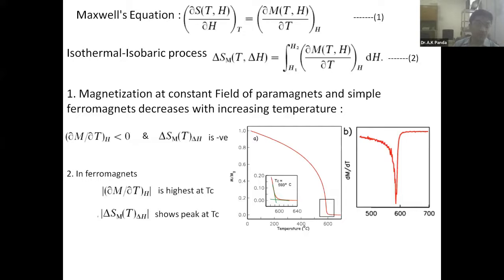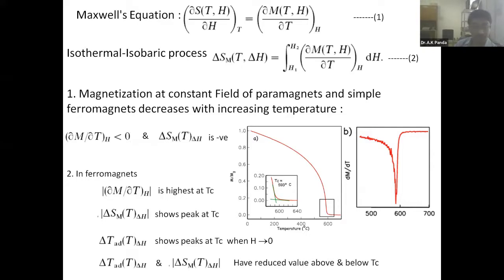So in the case of most ferromagnetics, this change of magnetization is highest at Tc, and we take advantage of it when we design magnetocaloric materials. Even at that temperature, delta SM shows a peak around the transition temperature, and in fact delta T adiabatic also shows a peak. On either side we have reduced values. So these fundamental aspects we take into consideration in our equations when we make the materials and apply them for measuring the properties.